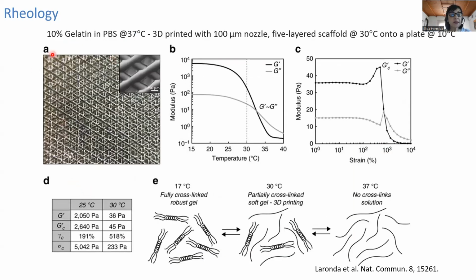As you see here, this is a sample made of simply gelatin in PBS at 37 degrees. It was printed with a nozzle just 100 micrometers thick, so a very fine structure. You can have here, this line is 250 microns. So you see here that you have pores around that value, 250 microns, and the lines lower than 100 micrometers because gelatin has shear thinning. So as you print, the faster the point that you are going to print is thinner than the diameter of the nozzle. This is a scaffold with 5 layers.